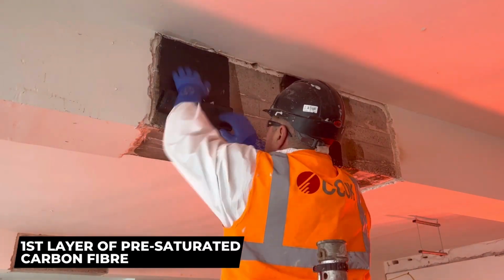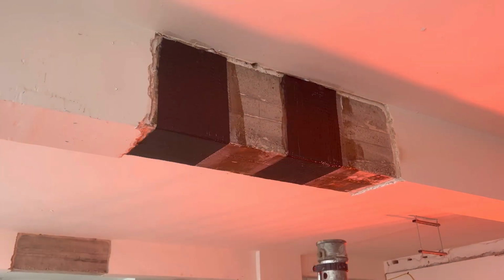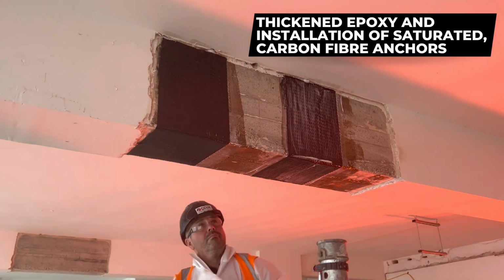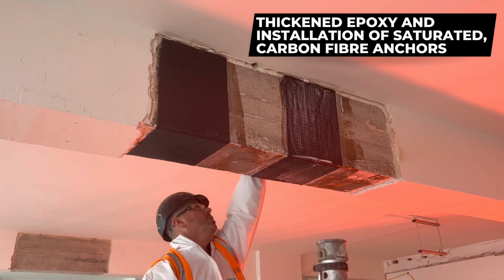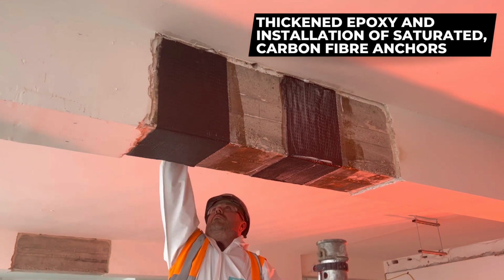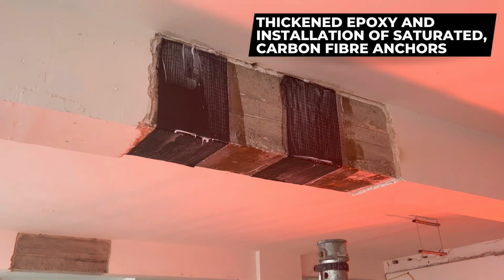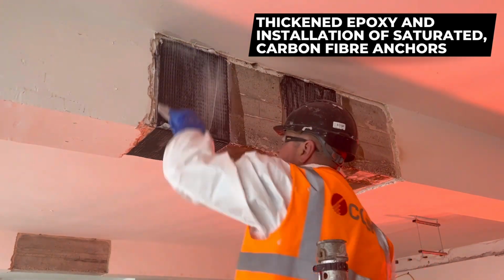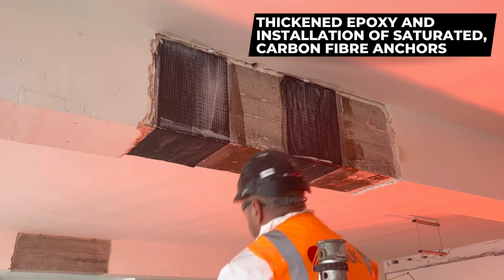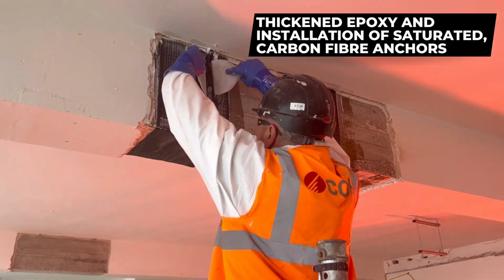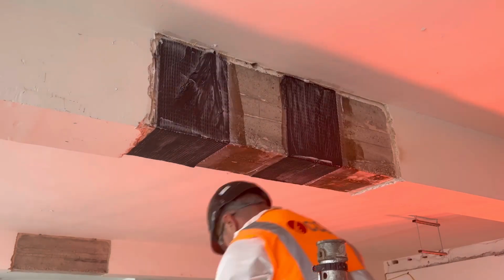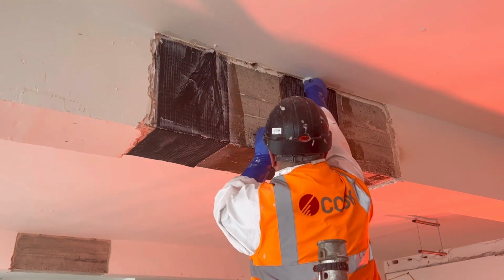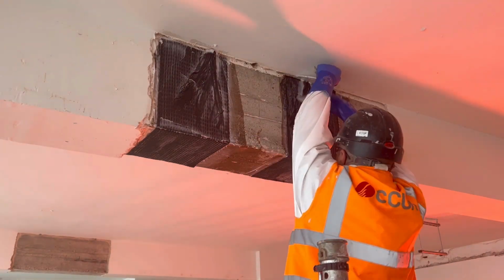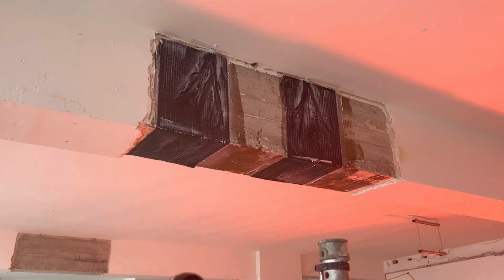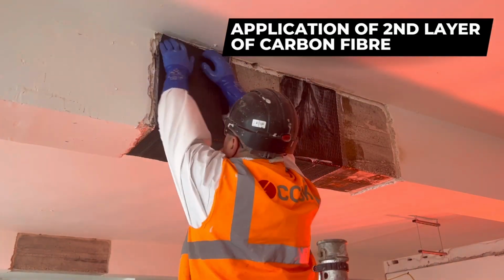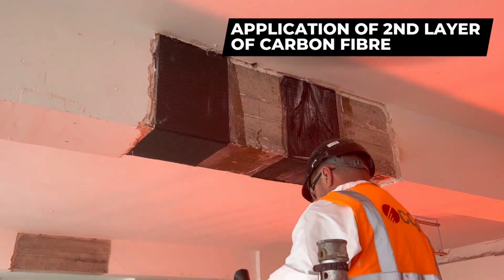And generally, whenever we are using fabric type of material for strengthening a structure, the application needs to be the wet layup method. There are still people out there who do dry layup. In dry layup, you just prime the area with the epoxy, put dry fiber on top of it and try and patch that fiber onto that primed area, and then put another coat of epoxy on the dry fiber. In doing so, nobody can guarantee 100% resin impregnation through each and every fiber. That dryness may lead to a debonding or delamination failure. For that reason, dry layup is more or less abandoned now. So it needs to be done as wet layup.